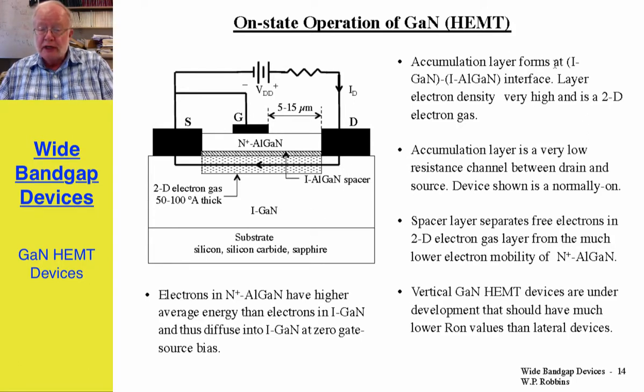This forms an accumulation layer at the interface between the spacer layer and the intrinsic gallium nitride, and the density of the electrons here is so high that it's sometimes called a two-dimensional electron gas. Numbers that are often quoted are 10 to the 13th electrons per square centimeter. The accumulation layer or two-dimensional electron gas is a very low resistance channel between the drain and source. And the device, as I've already shown, is a normally on device.